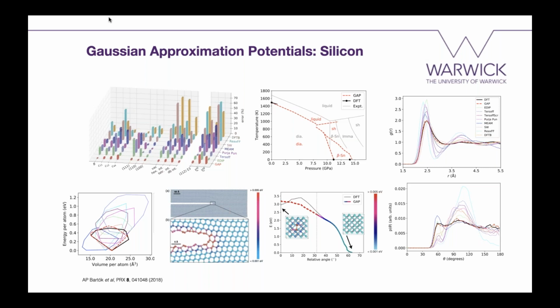And you can see that they scatter quite a bit, and only GAP is the one where the envelope of energies and volumes, this kind of convex hull, matches quite closely, and all the other methods find widely unrealistic configurations.